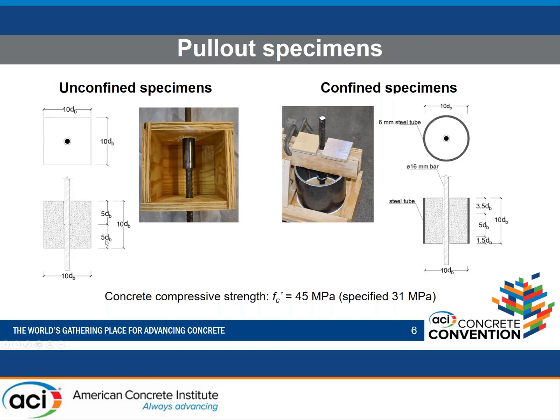The bonded region was 5 db. This is very commonly used when the local bond slip behavior is to be studied, because it gives a uniform bond stress distribution. And the unbonded region was done just to avoid the potential confinement from the bearing stresses during the test. So we will have more objective results for the bonded region. The concrete compressive strength was 45 megapascal, which corresponds to around 6.5 KSI.